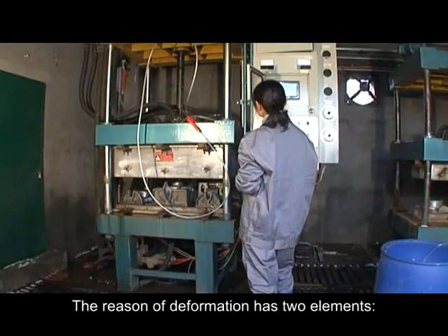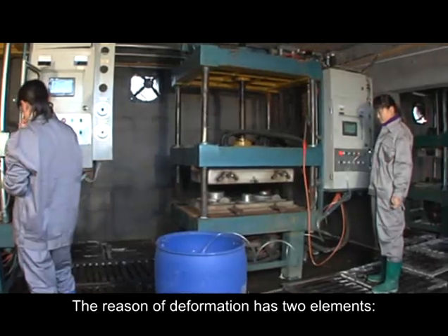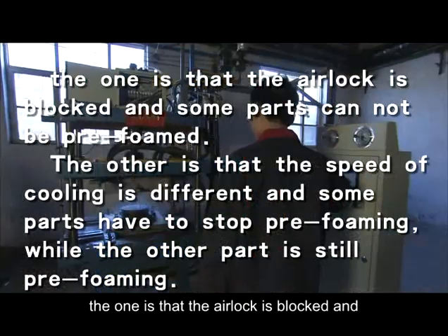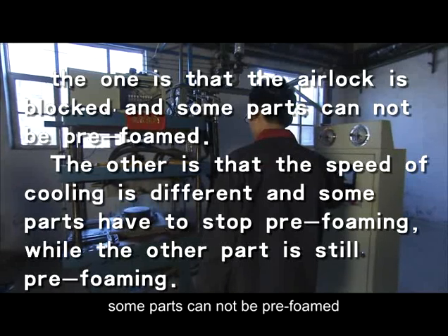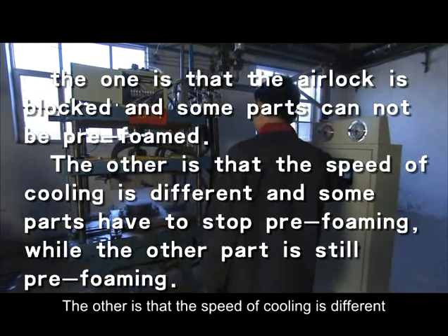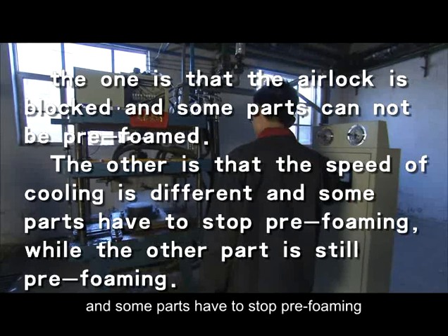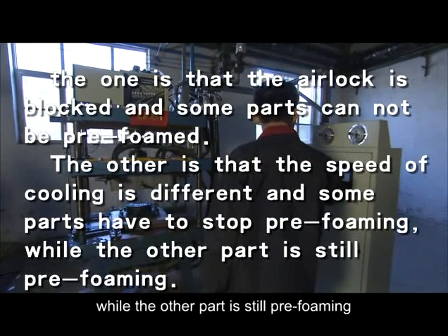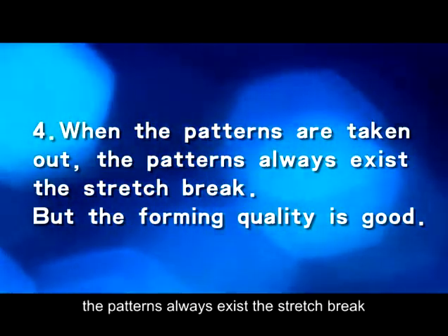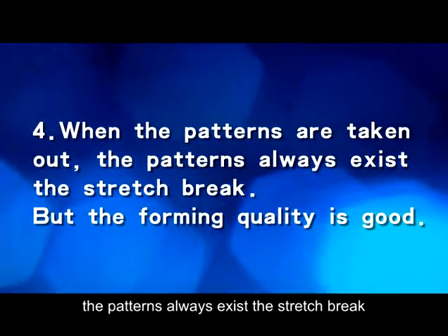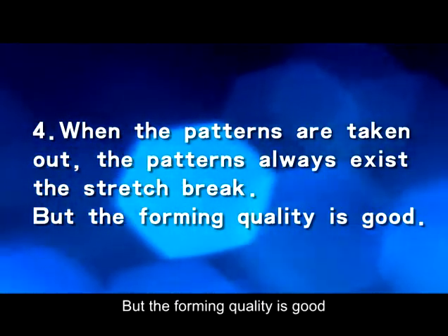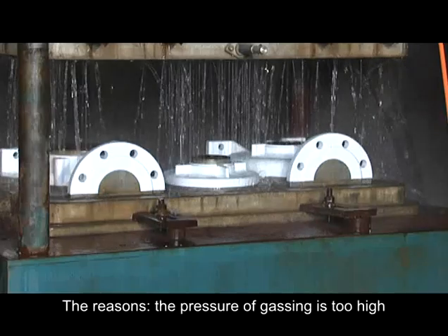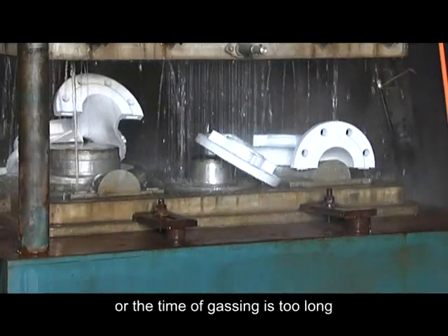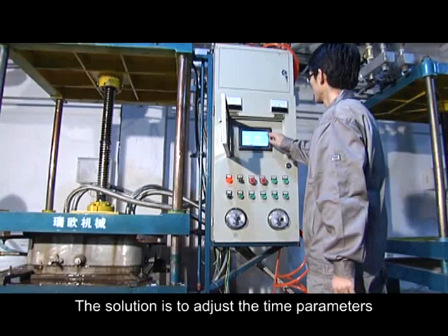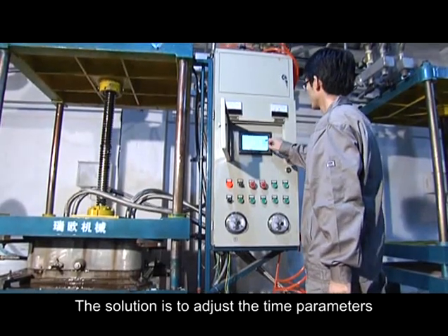3. Deformation. The reason of deformation has two elements. The one is that the airlock is blocked and some parts cannot be pre-foamed. The other is that the speed of cooling is different and some parts have to stop pre-foaming, while the other part is still pre-foaming. 4. When the patterns are taken out, the patterns always exist the stretch break, but the forming quality is good. The reasons: the pressure of gassing is too high or the time of gassing is too long. The solution is to adjust the time parameters.